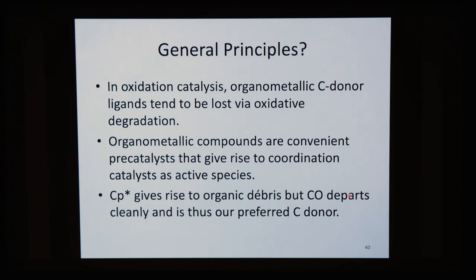So it looks like general principles are that organometallic carbon donor ligands tend to be lost via oxidative degradation. But that doesn't matter because they're convenient pre-catalysts that give rise to coordination catalysts as the active species. And we tried very hard to make the same blue species from coordination complex precursors without success. So there's something special about the organometallic starting materials that allows you to get clean production of the blue solution.